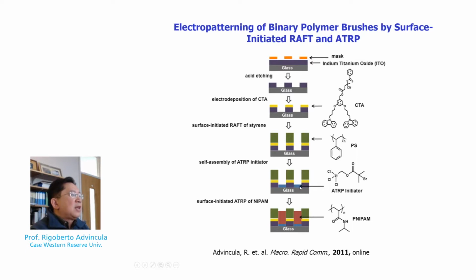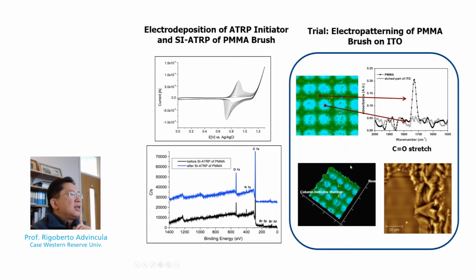But since the glass etch side can be modified by silane chemistry, we can actually graft by silane chemistry an ATRP initiator and grow another polymer, in this case PNIPAM. Here's an example of this chemistry where we've first demonstrated the grafting of a PMMA brush on an ATRP initiator. The image, as shown here by IR imaging, shows the image and the corresponding IR spectra for the carbonyl stretching of PMMA, and also verified by atomic force microscopy in terms of the morphology. And again, XPS, or X-ray photoelectron spectroscopy, can be used to verify this grafting.